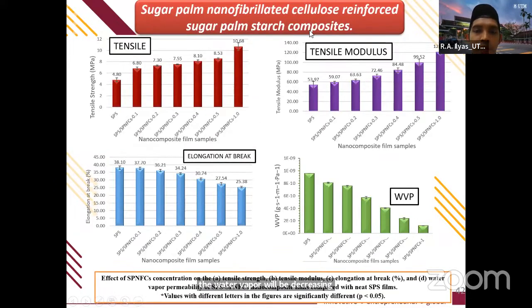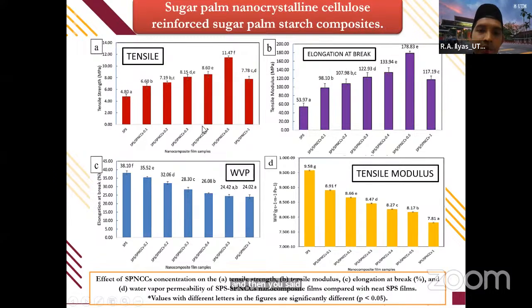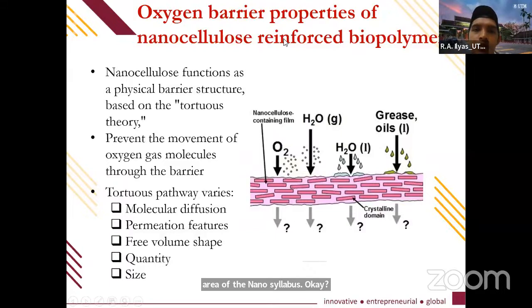And then besides that, the nanofibrillated cellulose. So these are the differences between the nanofibrillated and nanocrystalline. We include 0.5 for the nanocrystalline. However, for the nanofibrillated cellulose, we have to include 1.0. So why is it different? It's because of the surface area of the nanocellulose. Besides that, it also improves the oxygen barrier properties due to the tortuous path theory. When we include the nanocellulose fiber, the air needs to go through the tortuous path or the barrier. So this is the difference.